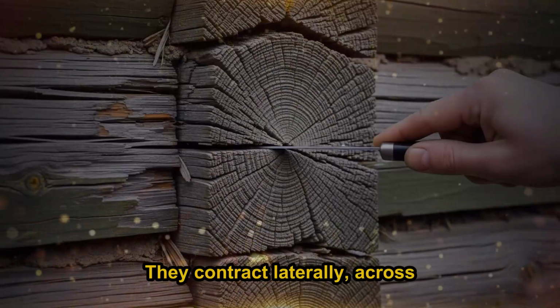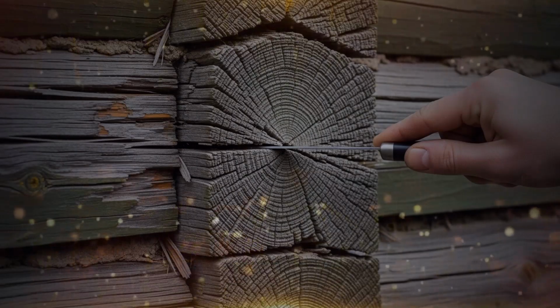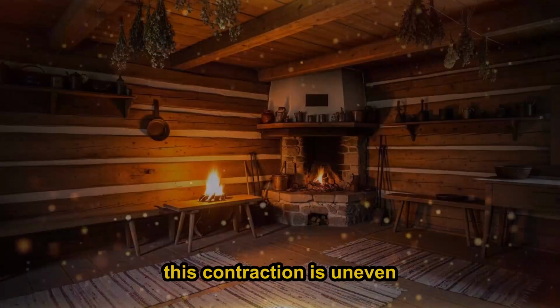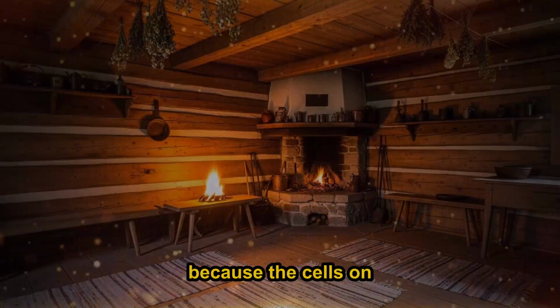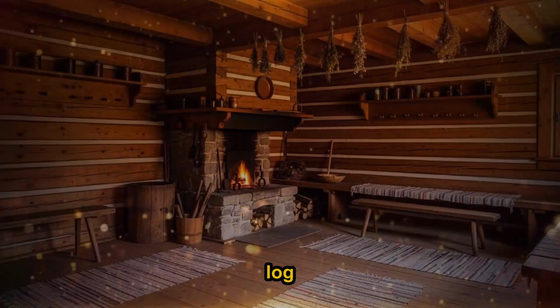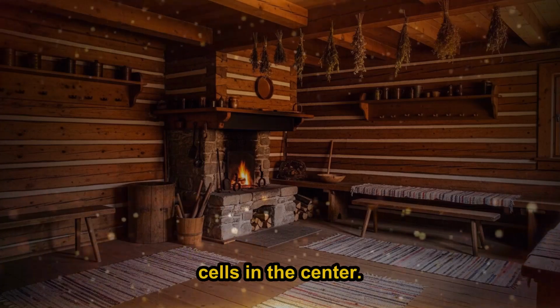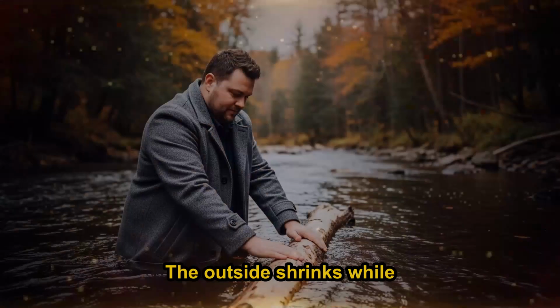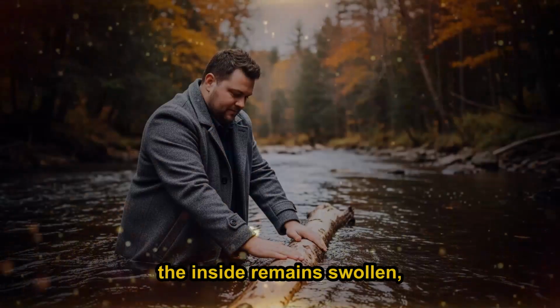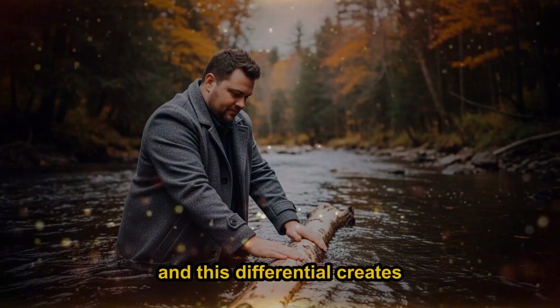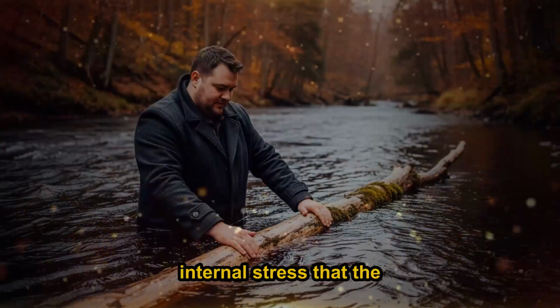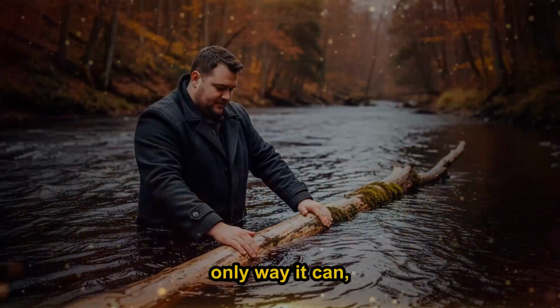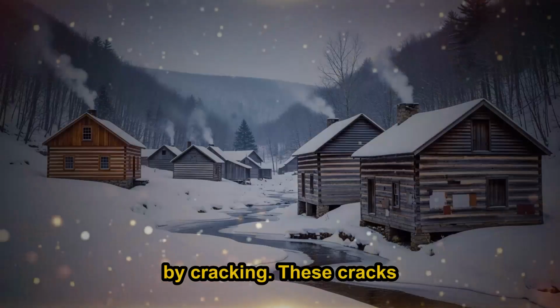They contract laterally, across the grain, not along it, and this contraction is uneven because the cells on the outside of the log dry faster than the cells in the center. The outside shrinks while the inside remains swollen, and this differential creates internal stress that the wood relieves in the only way it can: by cracking.